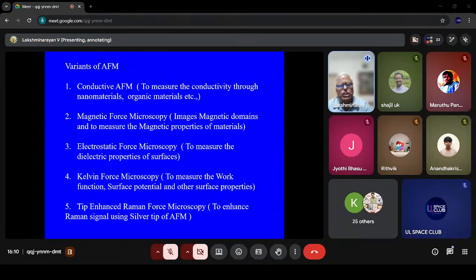And there are a lot of variants of AFM which are very popular nowadays, because you can do a lot of studies just by changing the AFM tip, using different materials for a particular purpose. The possibilities are immense. One is called, for example, conductive AFM, because AFM is classically used on non-conducting surfaces. You can also use a conducting AFM to measure the conductivity of nanomaterials, even organic materials. You bring the conductive AFM tip close to the sample, measure the current flowing between the tip and the sample, and use this for mapping the conducting and non-conducting regions on a surface. And magnetic force microscopy is used for imaging the magnetic domains and measuring the magnetic properties of materials.